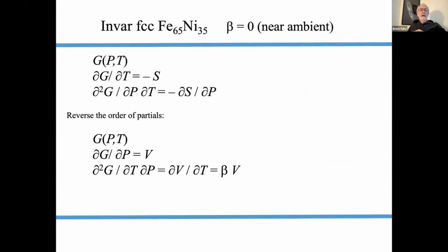So why pressure? Well, let me go back to my second thermodynamic slide here. This is the free energy as a function of pressure and temperature. And we can take the derivative with respect to pressure or temperature and then take the other one. So doing it in the order of the temperature first, this gives you the entropy, because this is minus TS as a term contributing to the G. Then we take the next derivative with respect to how the entropy changes with pressure. Now we can reverse the order of these differentiations, take the derivative with respect to pressure first, and that gives you a volume because it's a PV term in the free energy. Then do the temperature derivative, and we get how does the volume depend on temperature? That is the thermal expansion.